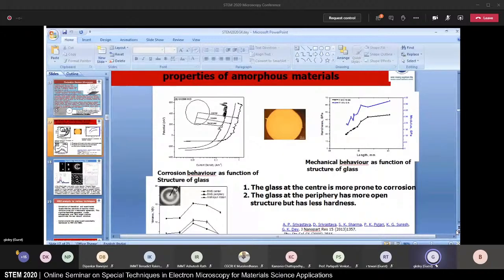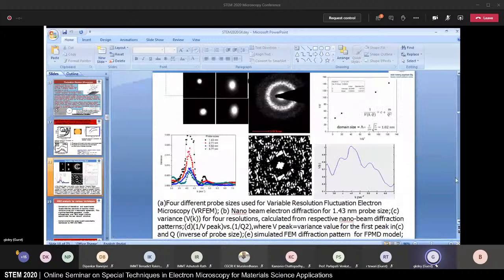The more accurate way to do fluctuation electron microscopy is to use the diffracted intensity, not the image intensity, but the diffraction in the diffraction mode. We make use of the intensity. So we do the same thing, that is, get the diffracted intensity and make plots like this of the variance, and this is the observed variance. And again, we assume a structure of the medium range order domain and make a diffraction pattern out of that, and then simulate the fluctuation microscopy plot the way it is shown here, and match this plot with the observed fluctuation electron microscopy plot. And if the agreement is good, then whatever medium range ordered structure we have assumed is the actual structure prevailing in the glass.